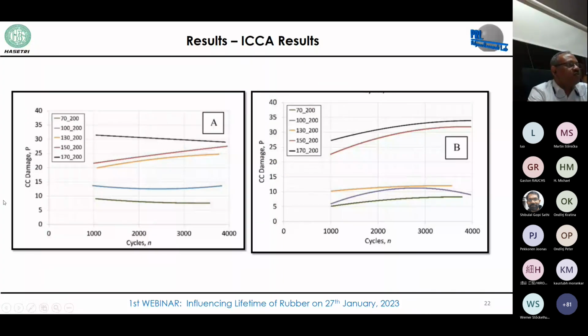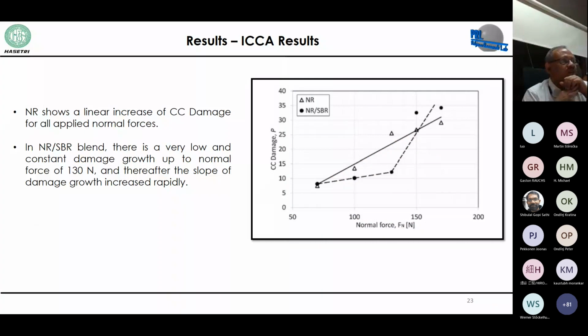And one interesting observation is that for the natural rubber based compound, the left side curve, till maybe the initial force level, natural rubber was showing higher damage parameter values compared to the NR SBR compound. However, it gets reversed at higher force level, which is explained in the next slides as well. So you can see very clearly that the NR curve is a smooth linear increase. However, NR SBR is passing through a small minima, and then it is again crossing the NR curve.